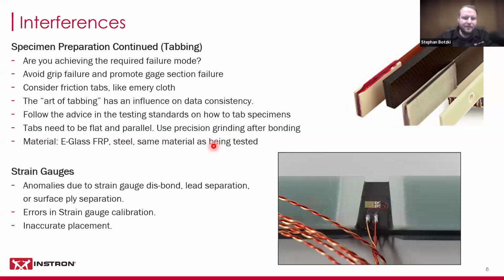A little bit on strain gauges here. Of course, strain gauges can also give you strain anomalies due to either direct gauge disbonding, or a potential separation of your leads to the strain gauge, or the surface ply of your specimen separating. So all of those things obviously are going to affect your strain measurements, and strain gauges are still required in a lot of tests to obtain your strain data. You could also have errors in your strain gauge calibration. For example, if you set it up in Blue Hill, you have to make sure that you use the right gauge factor for your strain gauges. And of course, inaccurate placement of the strain gauge itself will also cause you a lot of inconsistencies in your testing data because you're just not reading your strain data in the right orientation.